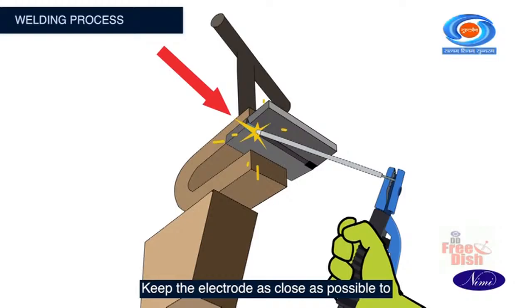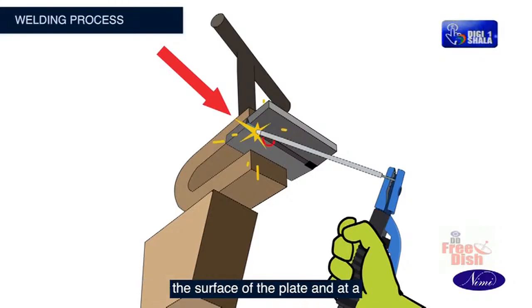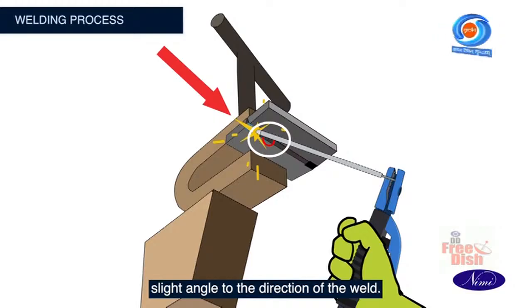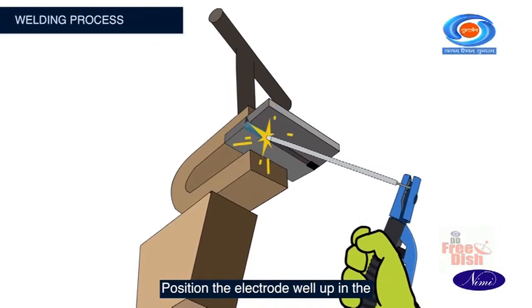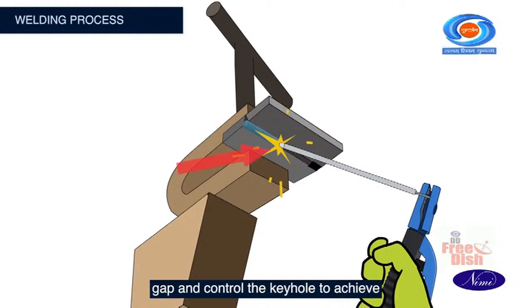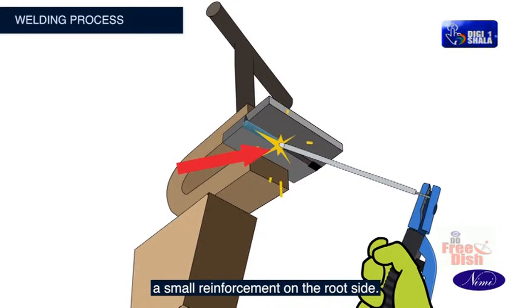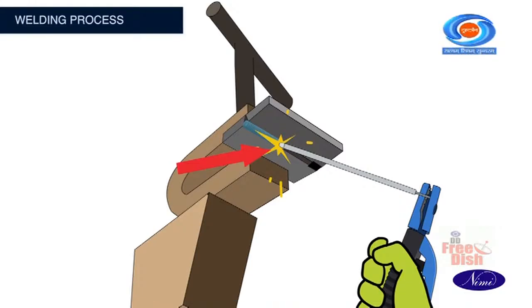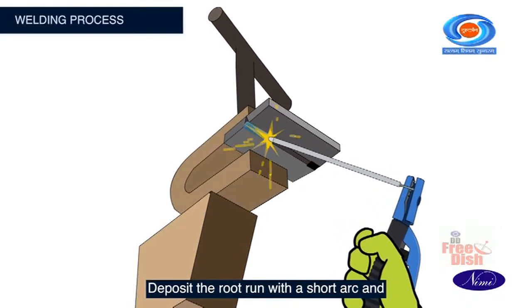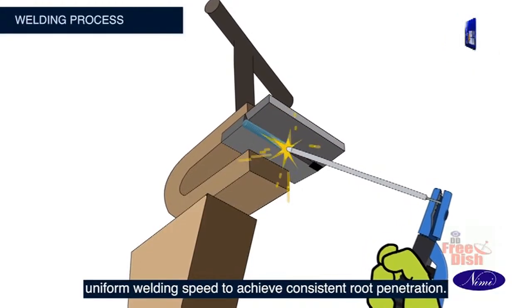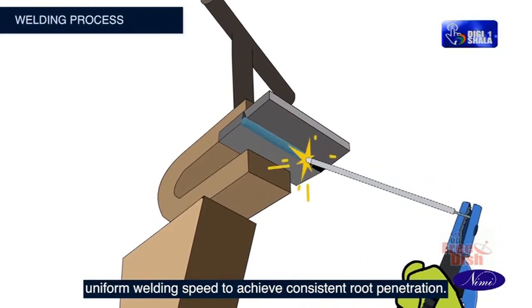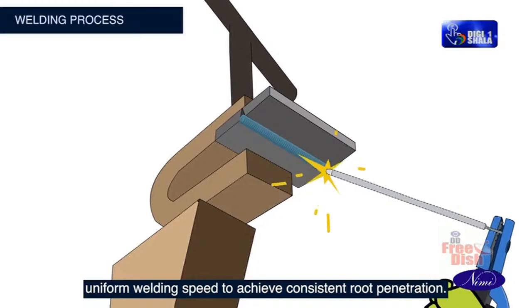Keep the electrode as close as possible to the surface of the plate and at a slight angle to the direction of the weld. Position the electrode well up in the gap and control the keyhole to achieve a small reinforcement on the root side. Deposit the root run with a short arc and uniform welding speed to achieve consistent root penetration.